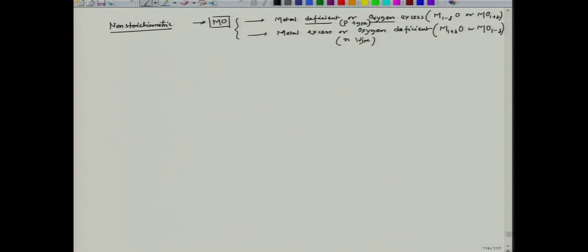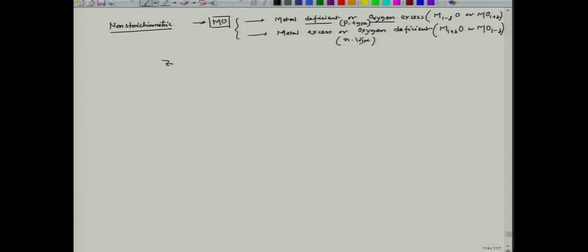And once we have these two situations, we would see that in both the cases, whether it is p type or n type, the diffusing species either could be metal ion or oxygen ion, depending on the typical situation we have. For example, if I consider zinc oxide, which is a metal excess oxide, I can term it as zinc 1 plus delta O.